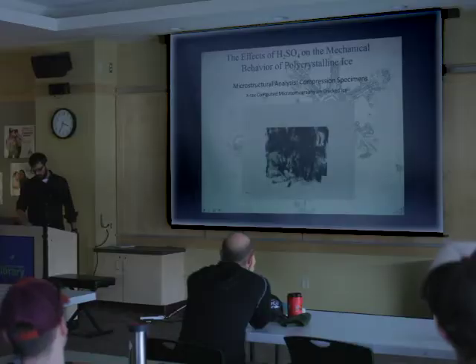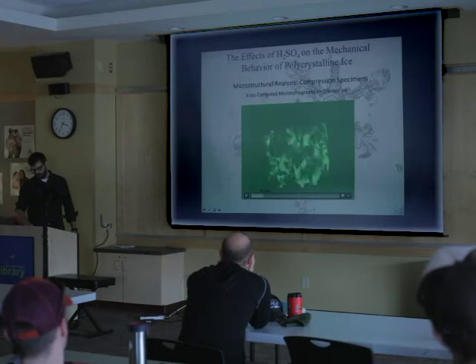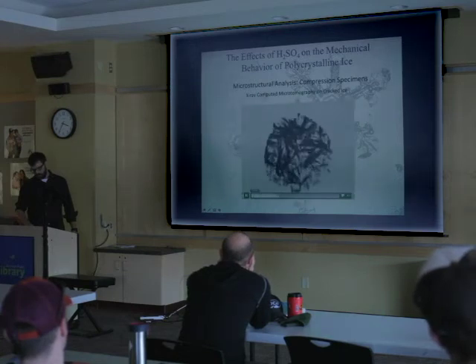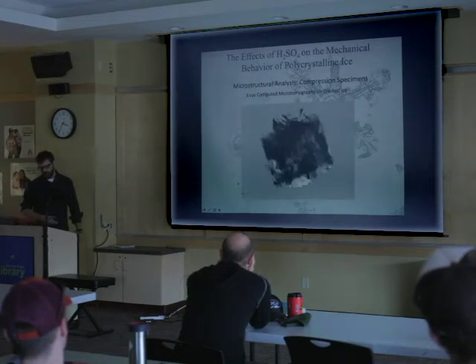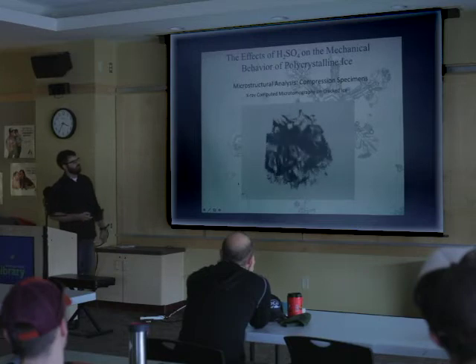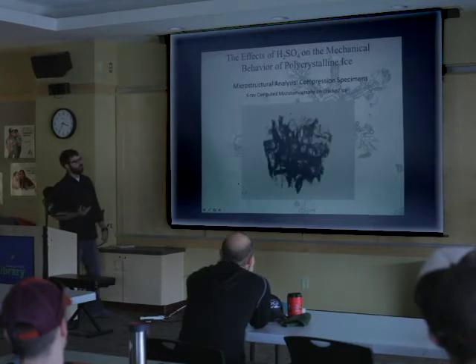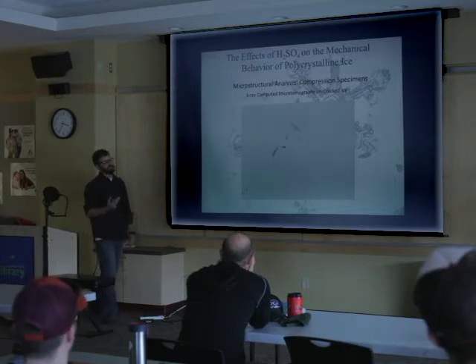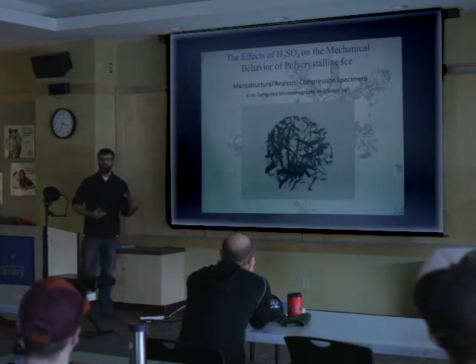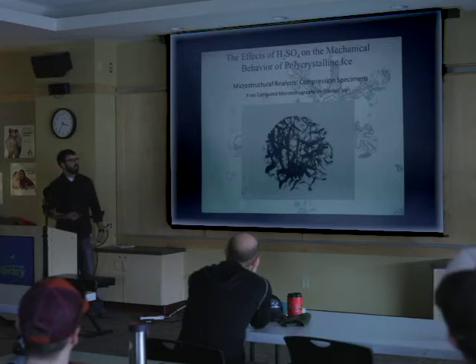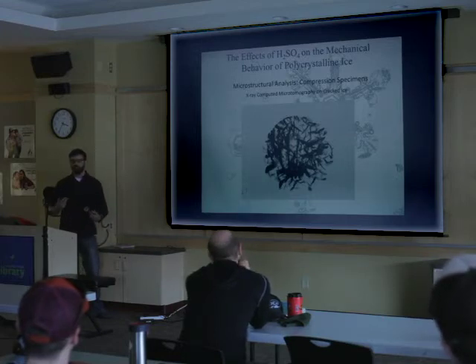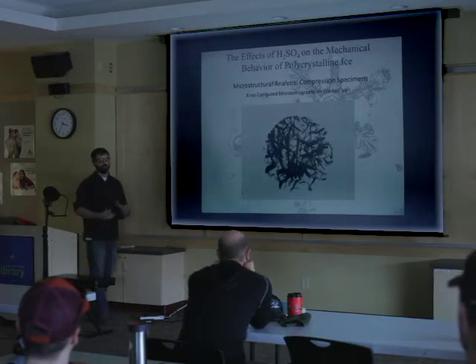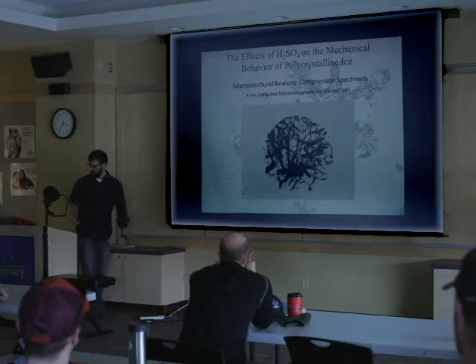This is a micro CT video of one of the samples that had been strained at a high strain rate. The black is the cracks in the ice, and the clear is just the ice itself. So we're able to quantify, by a volume ratio, how much air was in the ice that we would link to cracks that had happened. And of course, we link all these cracks back to happening at the grain boundaries where each one of those colored grains meet each other.